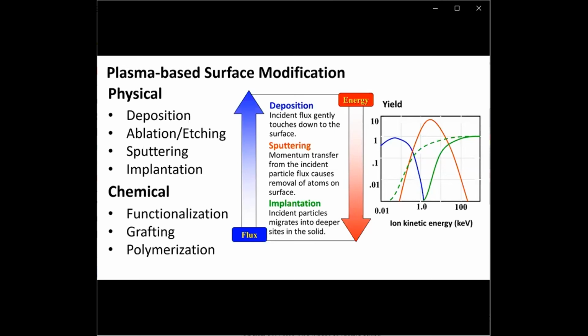With a slight increase in the incident energy, you are removing particles from the surface, which leads to ablation or etching. As you further increase the incident energy, then you are removing clusters of particles, which we call sputtering. And finally, at higher energies, the incident particle can penetrate the surface and become embedded, which leads to implantation.